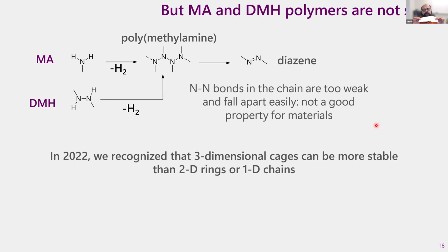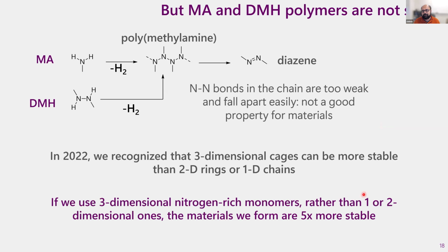Take that same sheet of paper and you have it as a sheet, you can notice that when it's a two-dimensional object, not just a one-dimensional object, it's flexible in two dimensions, but not so flexible in the third dimension. That's good. That's a little bit more stable. Take that same sheet of paper and you roll it up into a tube. Well, now this tube is rigid in both dimensions. And that's an analogy to what we do with the chemistry. We turn nitrogen chains into nitrogen cages, and they become far more stable and don't decompose as much. In fact, they become 5 times more stable. This unlocks everything that I'm going to talk to you about.